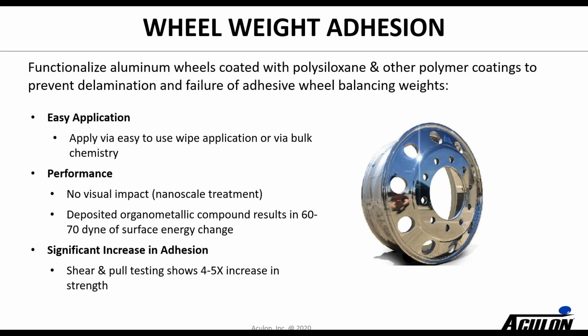With the wheel weight, this was really a problem created by wanting to coat the wheels with a brake dust repellent treatment. It's public information that Alcoa led the way on this and developed a nice coating for wheels, but then they unfortunately had an adhesion issue, which we were able to help them solve. And it's easy to apply. We sell this product in a wipe form, so you just open up a prepackaged wipe, wipe the section where the weight needs to be applied, and wait for it to dry. It's basically about a 30-second process. You apply the weight, and then you get excellent adhesion.